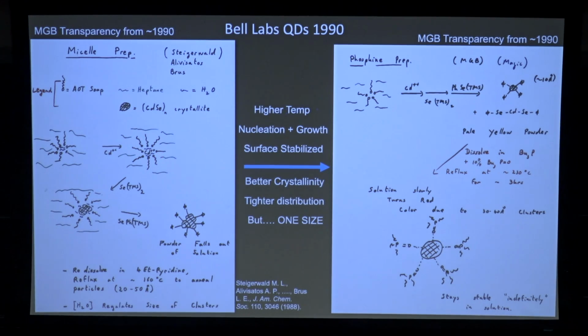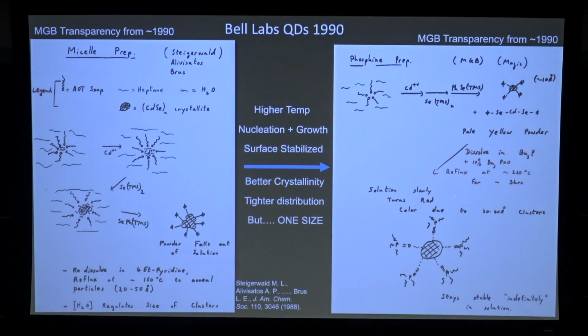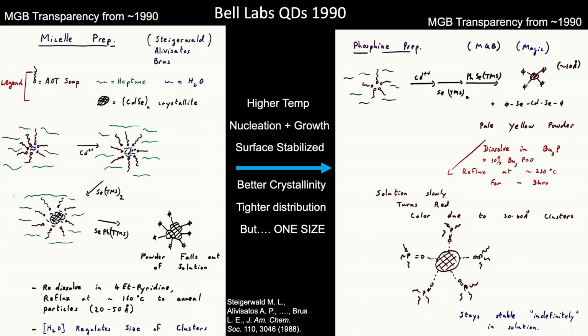So this is the idea of nucleation and growth that is well known in physical chemistry from the 1950s. So you have a seed crystal here, and you slowly grow it out. And the color turns red because the wavelength of that electron gets longer, the energy is lower, so it looks redder. And you get this particle surrounded by these phosphine oxides that are stable pretty much indefinitely in solution.